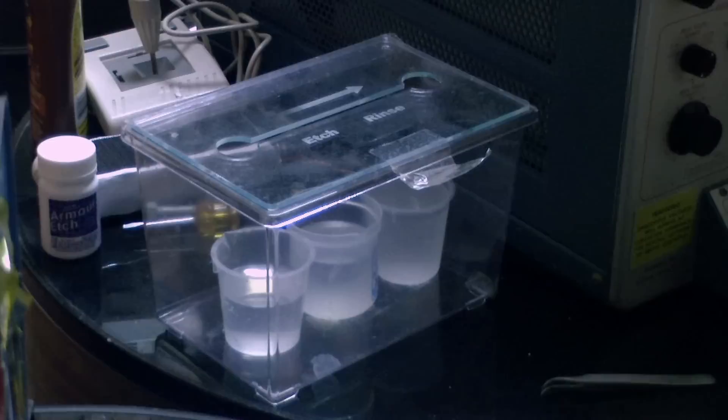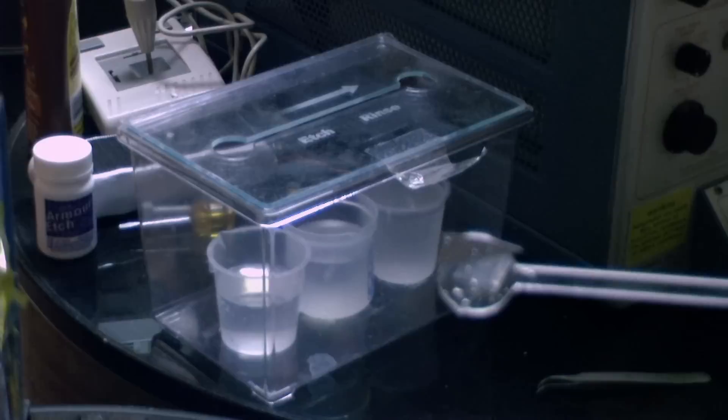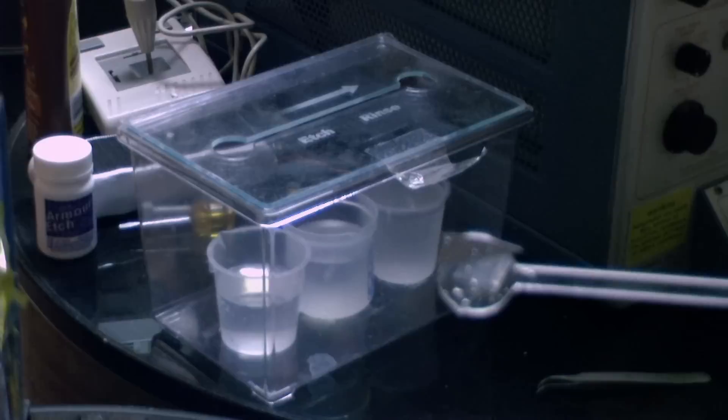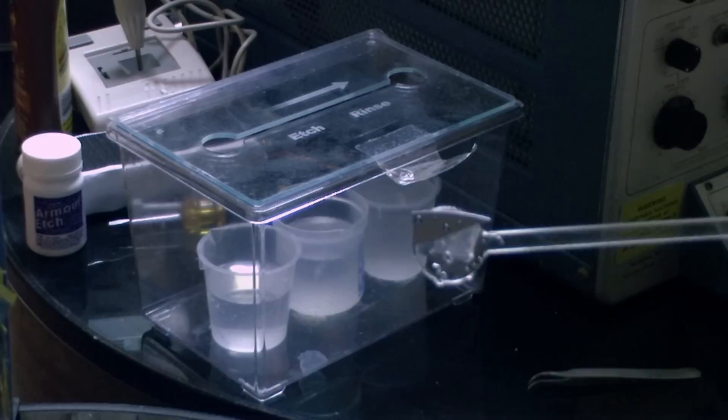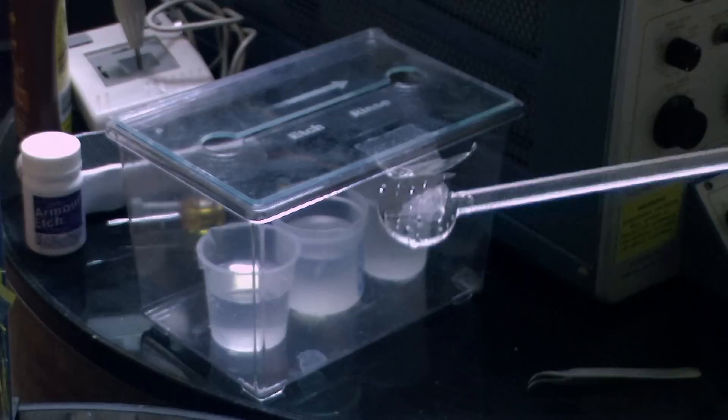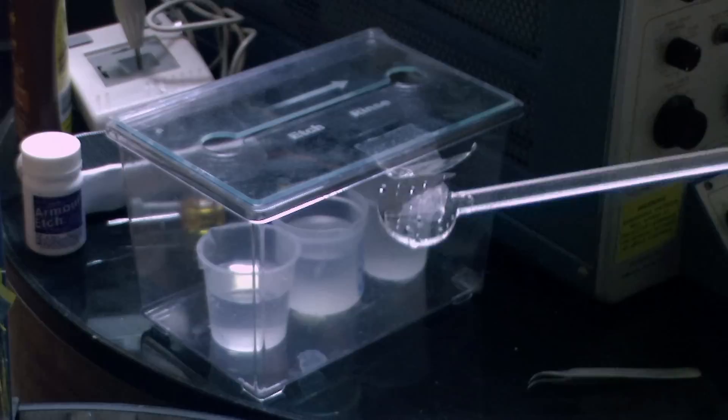Okay, here's something really quick. Let me see if I can adjust the focus here. Now, when silicon is bare, no oxide, it becomes hydrophobic. It means that water will bead up on it. And I've just pulled this out of the etching tank, and the water's beading up. So I must have the native oxide removed. All right, now I'm going to dry this off and really come back and do the hot point probe. And I didn't die having to go in there messing with the hydrofluoric acid. My bones do feel a little gelatinous, though.